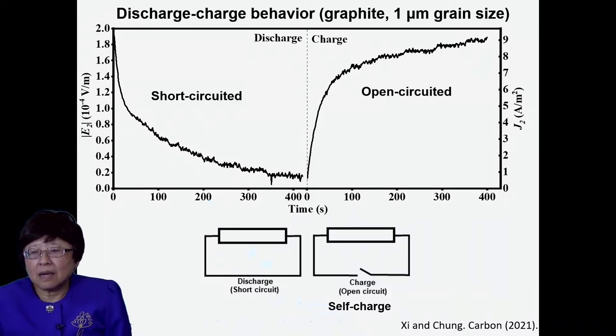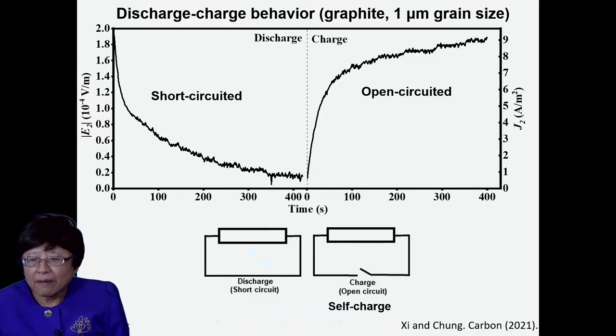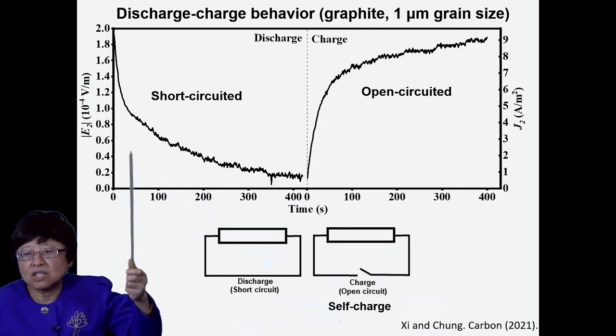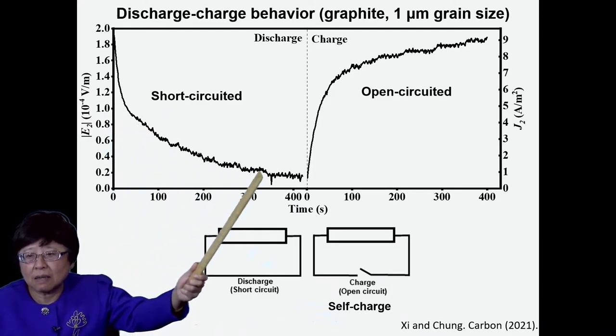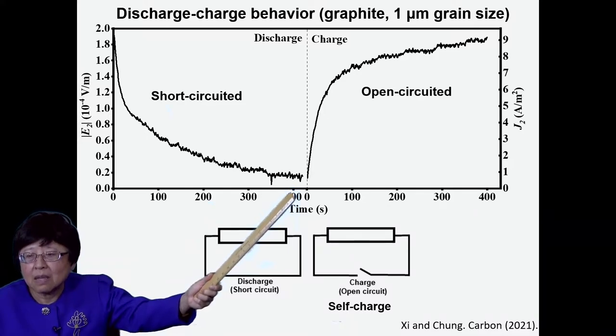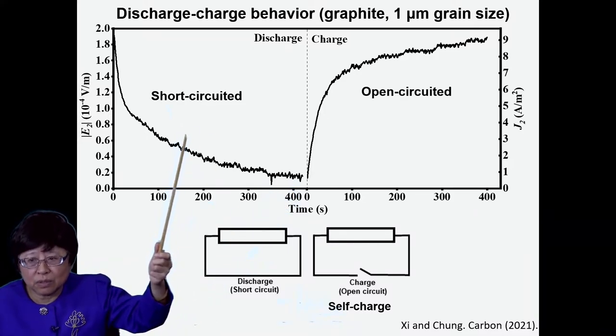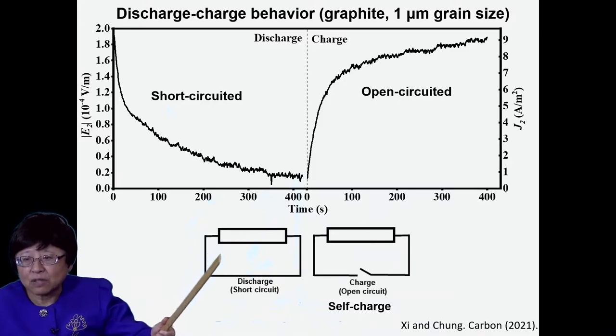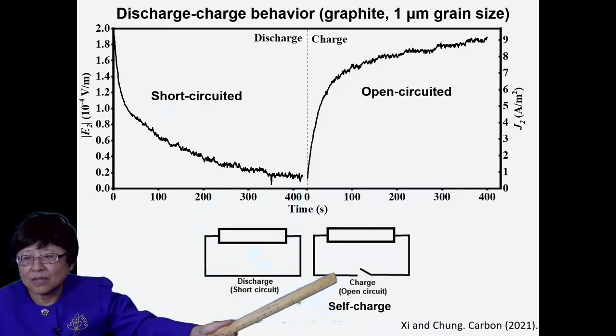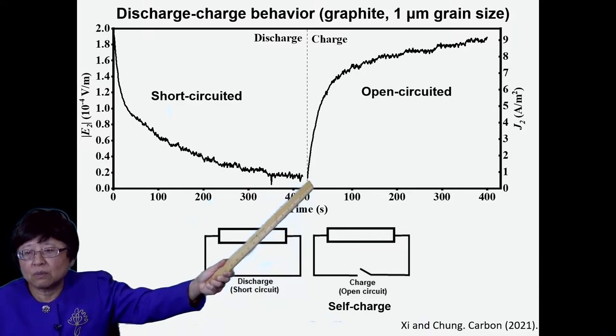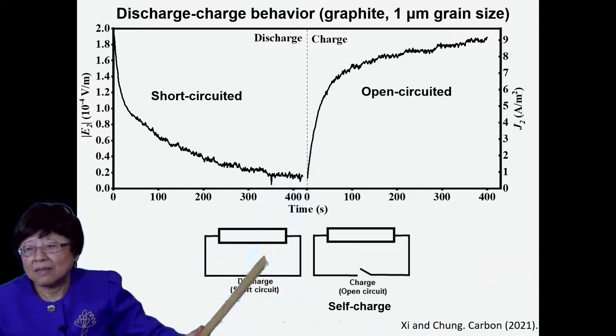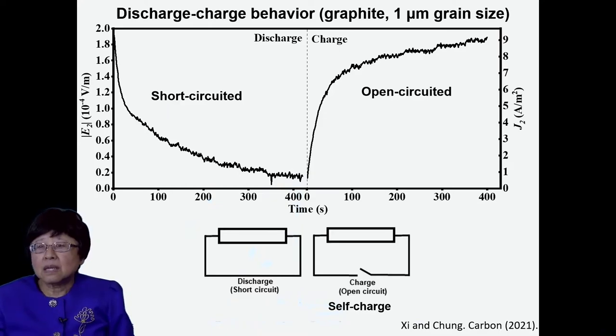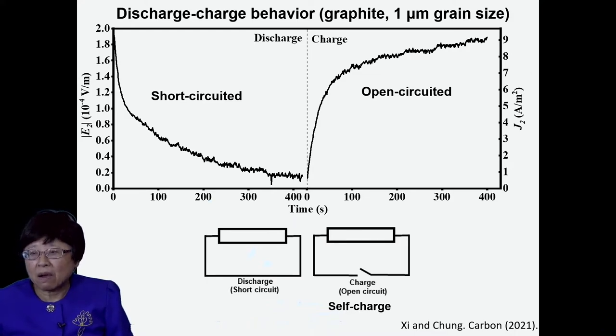Now, this electret with its inherent voltage, or inherent electric field, upon short-circuiting, would get discharged so that the voltage or electric field would gradually decrease to zero. That occurs upon short circuiting. However, afterward, if you open circuit it and let it sit, the voltage or electric field would be recovered. And that's self-charge. And this is the result for graphite with one micron grain size.